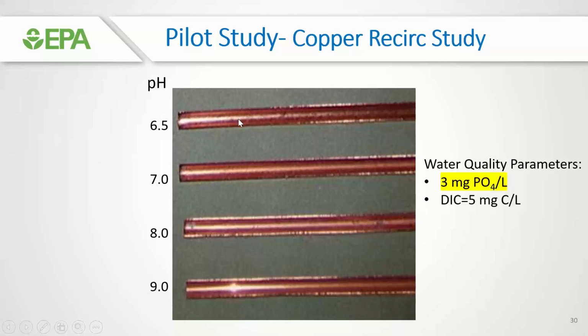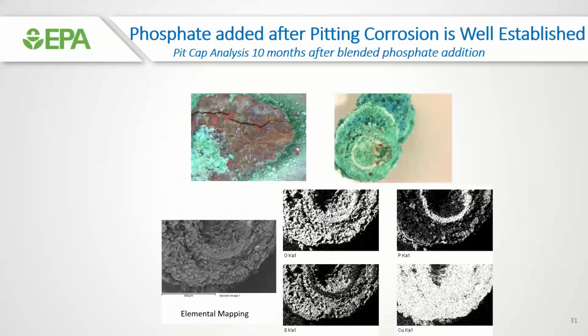Like the uniform corrosion experiments, pipes look brand new. So there may be something to the benefit of adding orthophosphate in preventing pits from forming in the first place. But can you stop a situation that's already going, we'll say a long-term issue with pitting corrosion that's well established? So this is actually full-scale data: we received pipes from a community after 10 months of adding a blended phosphate.